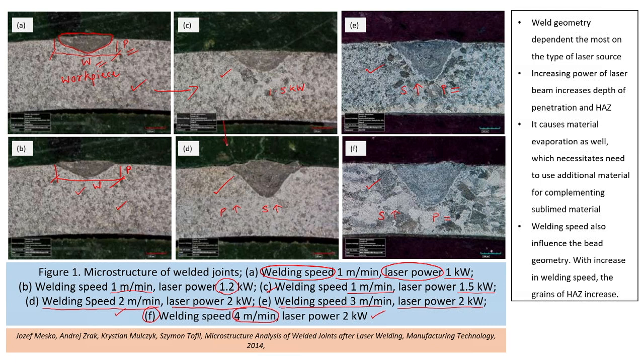From C to D, we increase speed — reducing interaction time — while also considerably increasing laser power. The reduction in interaction time increases power density. As a result, you can notice a considerable enhancement in both width and penetration depth. Both welding speed and laser power are major influencing factors during weldment formation in laser welding.